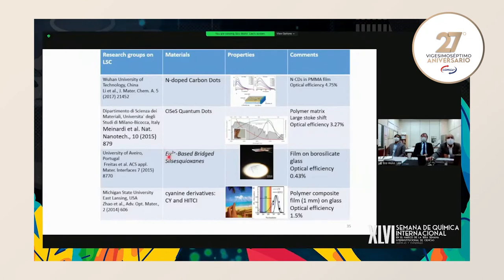Another is europium-based bridged silsesquioxanes, which were fabricated by Portuguese groups, and it has quite low optical efficiency because europium has very narrow emissions, and narrow emissions may cause low efficiency. And this one is CY7-HITCI organic LSCs, fabricated by Michigan State University, USA, and it is highly transparent, around 88%. But the efficiency is quite low, 1.5%.